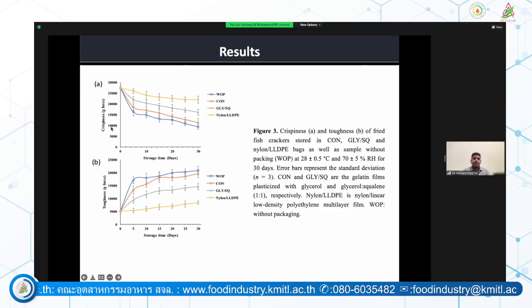And here we can see the textural property, crispiness, and we can see there is a decrease in crispiness for control samples, and similarly the crispiness reduced in the squalene incorporated bags to approximately 50% of the change compared to that of nylon bags. And a similar observation was found in toughness. So the toughness started reducing in the first 5 days itself in the control samples, and we can see still lower toughness observed in the crackers stored in the squalene and nylon bags for several days.